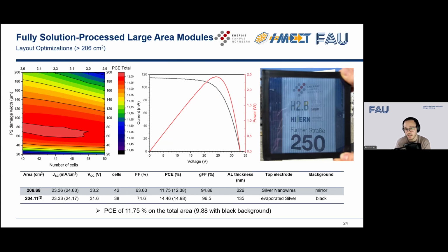I also gave you the thickness of the active layer. And if you compare it to the evaporated silver, of course, it's not as high because the silver is more conductive, the FF is higher, and so on. But it still shows that we mainly lose due to the conductivity of the top electrode. And with the optimizations that we did, we can significantly reduce the losses compared to the evaporated silver.